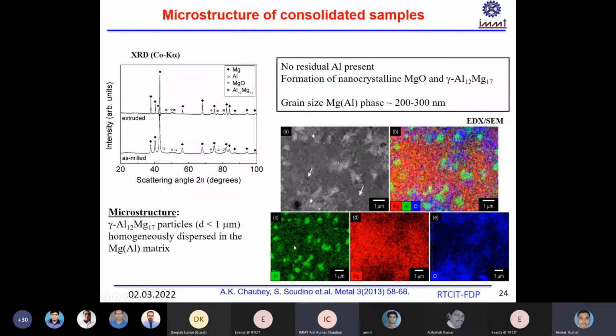So this is the aluminium distribution you can see. So here by mechanical alloying, we could get more and more aluminium in solid solution, as well as we are reducing the size of the aluminium gamma phase, as well as distributing it throughout the matrix. Distribution of these particles goes through the whole matrix. So our aim was that the gamma phase should not solidify along the grain boundary, and also to reduce the gamma phase. So by this powder metallurgy, this objective was achieved.